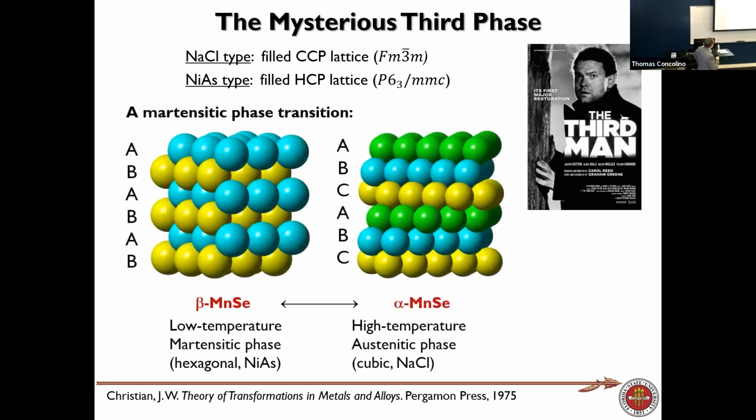So what we do is we're just shifting our AB layers to ABC layers, vice versa. We go from CCP to HCP packing in this case. And of course, what we expect happening, based on the conversion from this structure to this structure, is you have to go through some orthorhombic intermediate. If you look at the group-subgroup relationship in space groups, you'll have to go through that route and convert the structure to orthorhombic. And so now we really hope that with high resolution synchrotron data, we'll get the answer really soon to what's happening here.